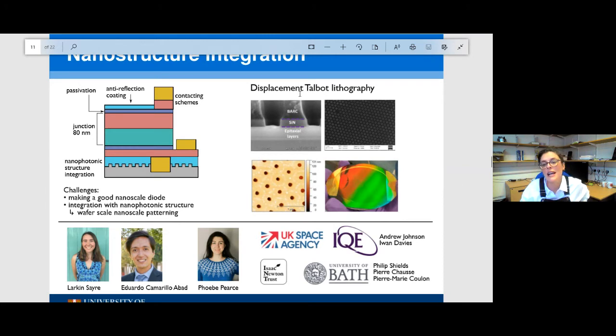Displacement Talbot lithography is an emerging technique that's mainly been applied to LEDs at this point, so we're borrowing from that knowledge. It actually takes advantage of the fact that diffraction is taking place, and of the fact that we are using a grid. So we have an array here that allows us to have a separation between the sample and a mask, and we use this Talbot effect of self-images at a fixed distance from the mask in order to pattern into a resist. And that's what we've done.